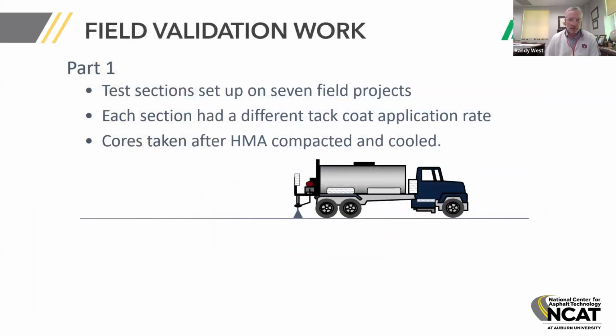So we also did, as part of this project, a field validation phase, and there are two parts to this. Part one was where we went out and built test sections on 7 field sites around the state. At each of those projects, we had 3 different application rates, and we took cores after the asphalt overlay was compacted and cooled.